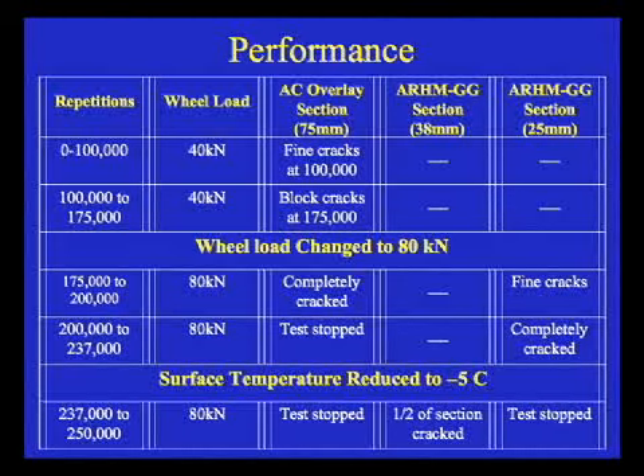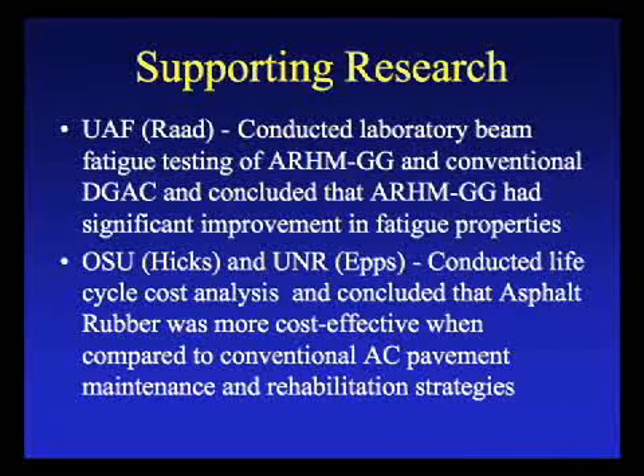So you can see what this test shows you is that when the conventional mix is in the best condition it's going to be in, because the rubber is going to age slower, the thought would be that the rubber would be better later on than the conventional. The best that the conventional would be in resistance to cracking would be at the beginning. And this really validated the reduction in thickness, and it did validate that it is a very conservative approach.